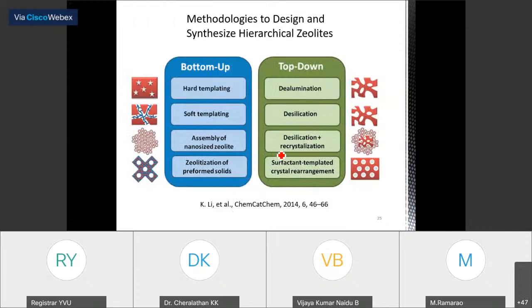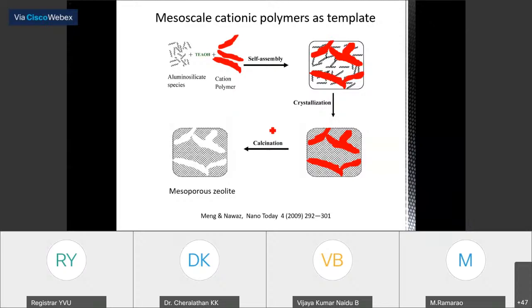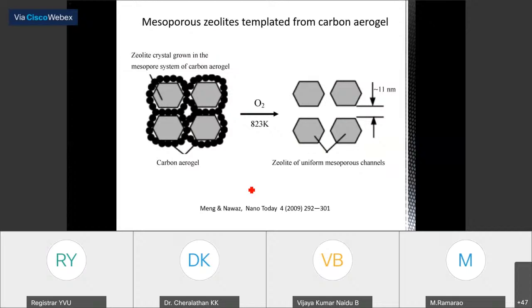Okay? So there are different ways reported in the literature to design this kind of hierarchical zeolites. You have bottom-up approaches and top-down approaches. And some of the ideas I want to show you here. So you can have a cationic polymer, and you can build your zeolite crystal surrounding this cationic polymer. And ultimately, finally, when you remove this cationic polymer, you will get a mesoporous zeolite. This is an idea.